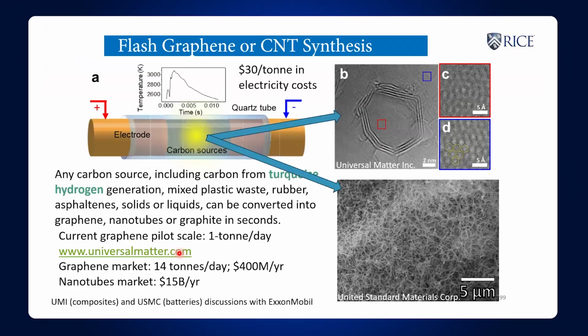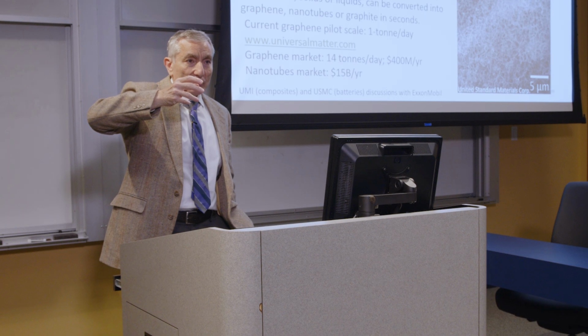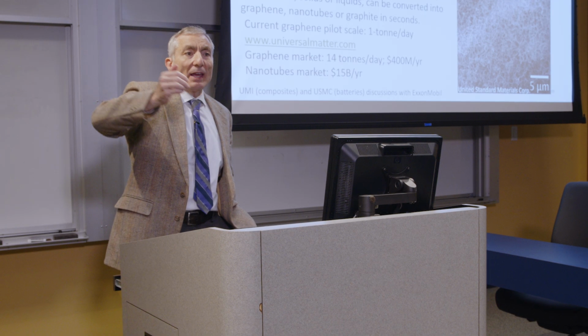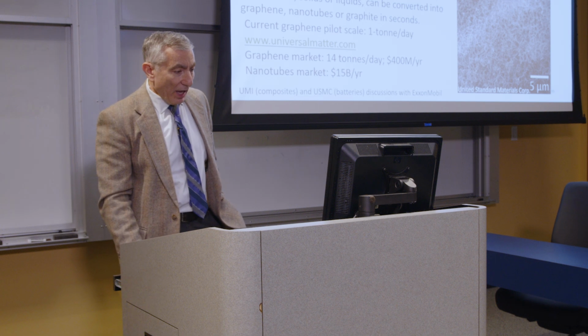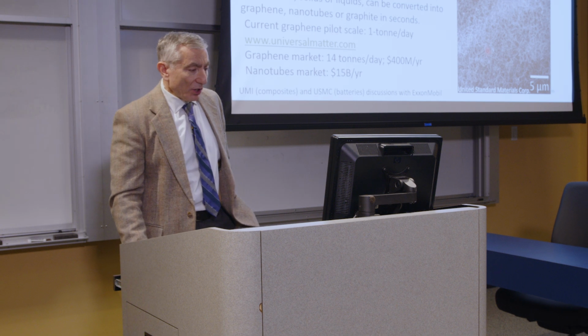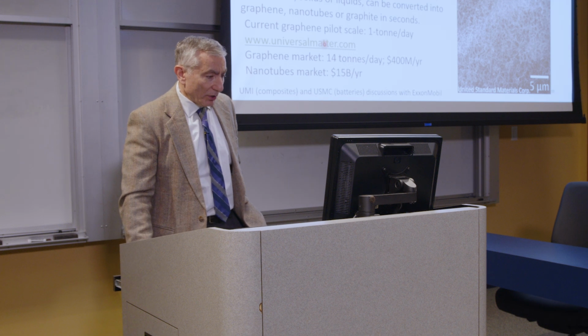All right, so remember what we can do is we can put any carbon source between 2 electrodes, flash it, we can turn it into graphene, or if we add a little bit of iron, say 1 weight% iron, as say iron chloride into this, when you flash it, that iron acts as a nucleus on which the nanotubes grow. Remember, you get this carbon, it covers the metal particle, and then that grows a nanotube. And so you get nanotubes coming out of this. And so that's gone into this company, Universal Matter, which we talked about last time.